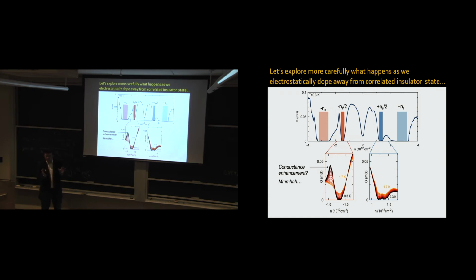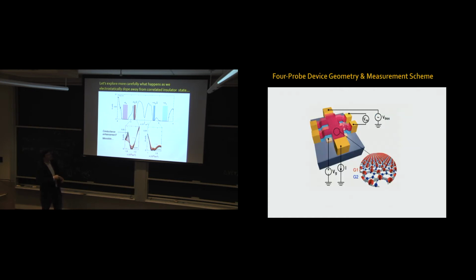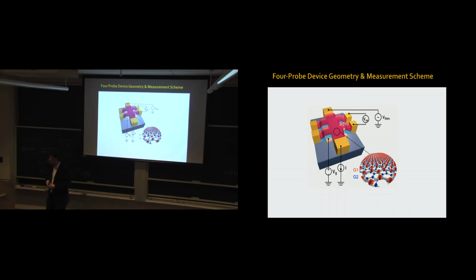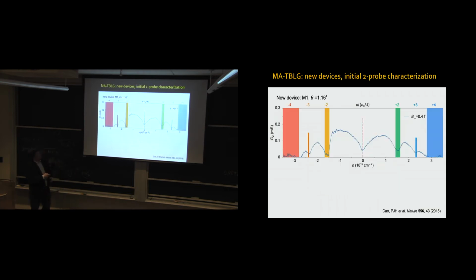So I told my students, let's make four-terminal geometry devices. Basically, you do the exact same fabrication, except that now you have several electrodes, and you can run a current between two electrodes and measure the voltage drop within your device, and you eliminate all parasitic resistances. So let me show you data from another device. This is a 1.16 degree device. This is the conductance. We first characterize these devices in two-terminal geometry because it's simpler. So this is a two-terminal conductance as a function of density. We've got this V-shape near charge neutrality, insulating states at 4 electrons or at 4 holes per superlattice unit cell. We have stuff going on at 2 and -2.